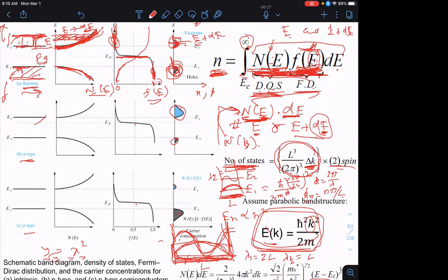And this derivation, like I said, although I'm not doing it, is given in one of the appendices over here. You might want to go through that, even though I'm not going to make you responsible for it in the exams. Now, what does this box physically correspond to? Well, in our case, the length of the box will correspond to the length of the crystal that I'm dealing with. So if you have a longer semiconductor crystal, L becomes longer and the spacing between the allowed k states decreases. Therefore you get more densely spaced k points.